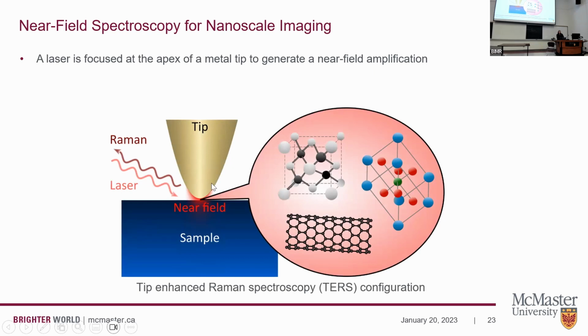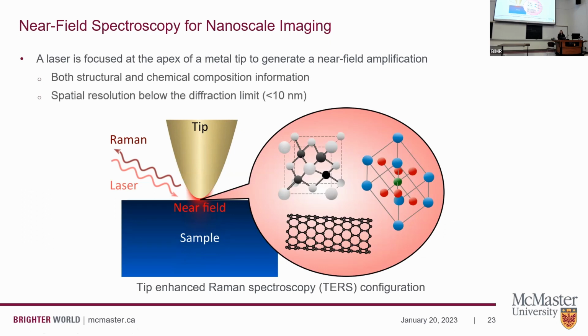The tip, just like in AFM, is placed in feedback with the sample surface. And the fact that we focus the laser at this interface will generate what we call a near-field amplification. So that means that, for example, the Raman signal will be significantly enhanced. As a result, we can obtain both the chemical and the structural information with a spatial resolution similar to that of an AFM, which is about 10 nanometers or less, way below the diffraction limit.